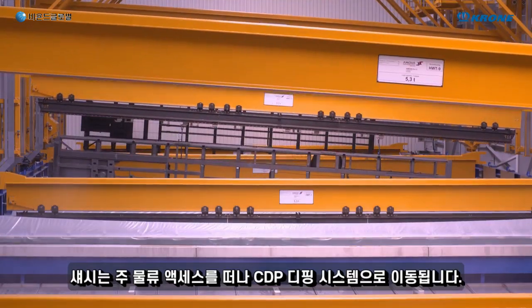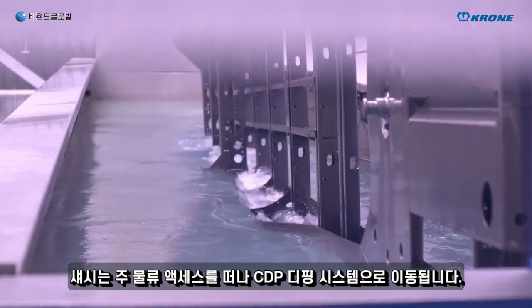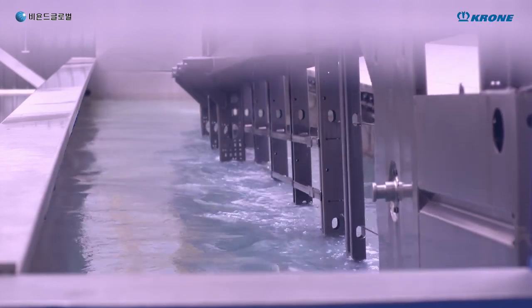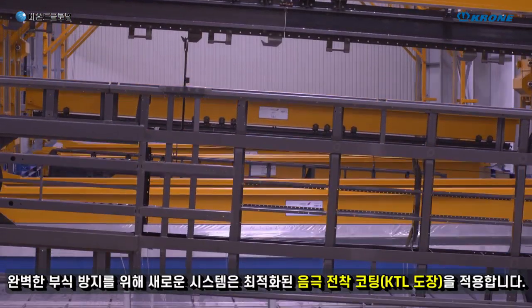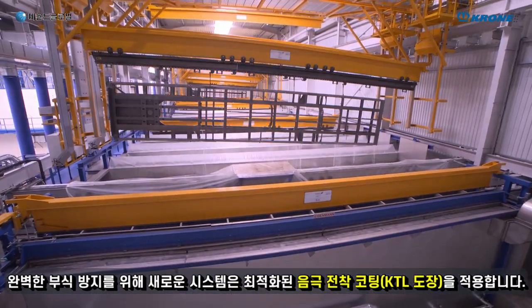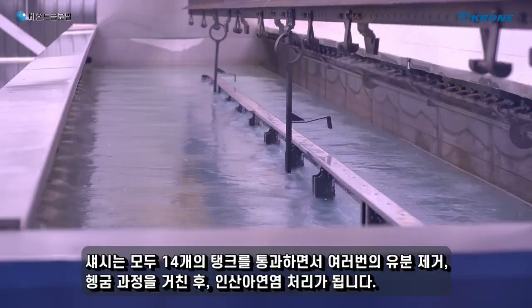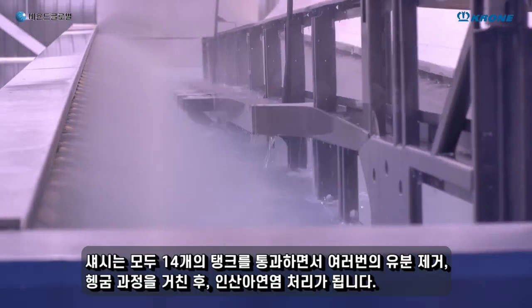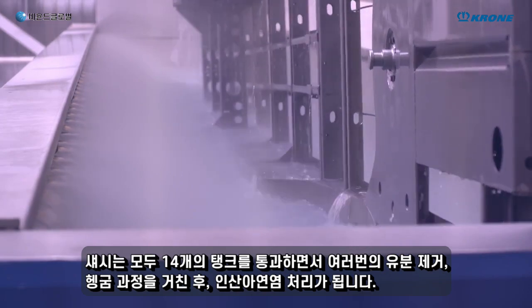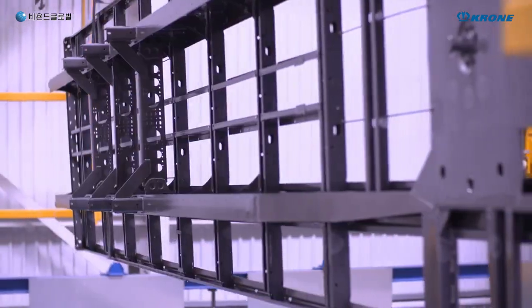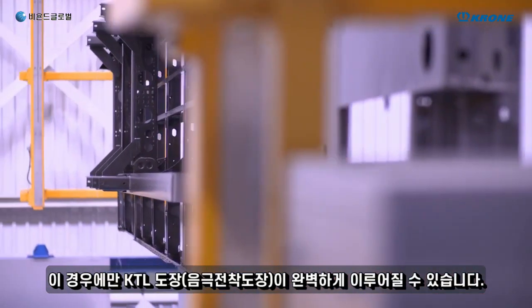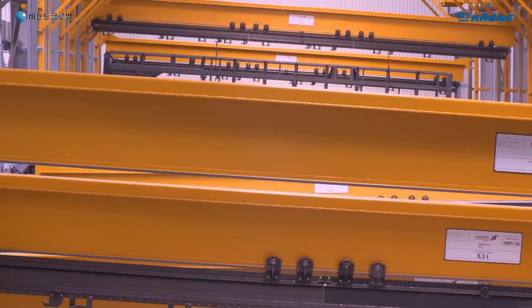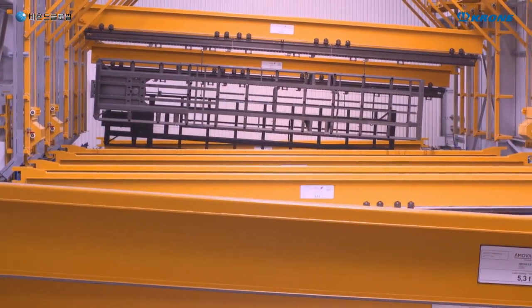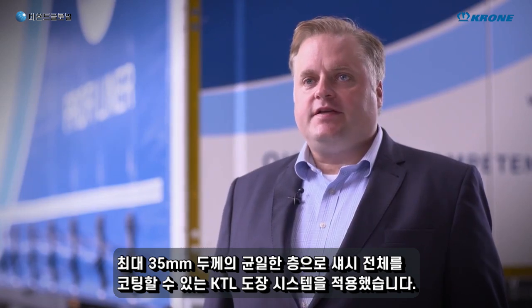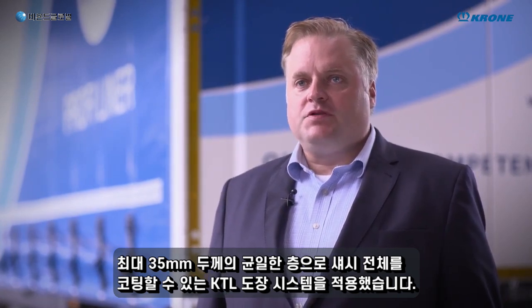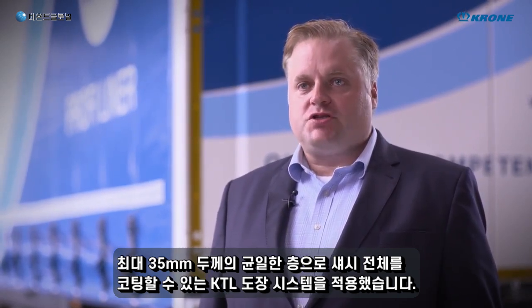The chassis first leaves the main logistics axis to go to the new CDP dipping system. For perfect corrosion protection, the new system applies an optimized cathodic dip coating. Altogether, the chassis pass through 14 baths where they are degreased, rinsed and zinc phosphated, among other things. Only then does the actual CDP procedure take place. We chose a CDP dipping paint that coats the entire chassis with a homogeneous layer up to 35 μ thick.